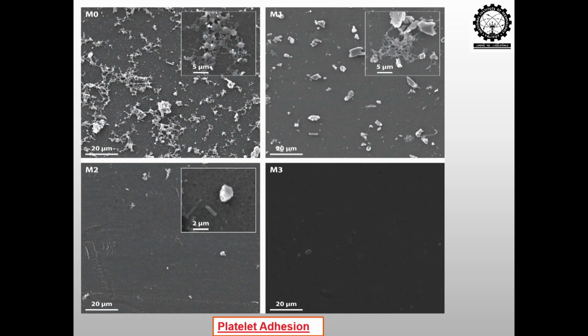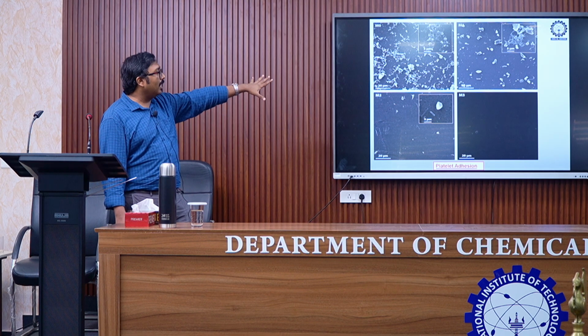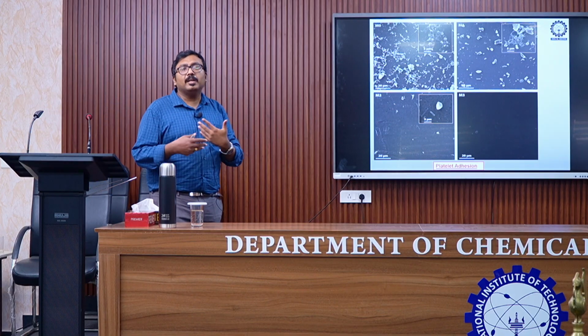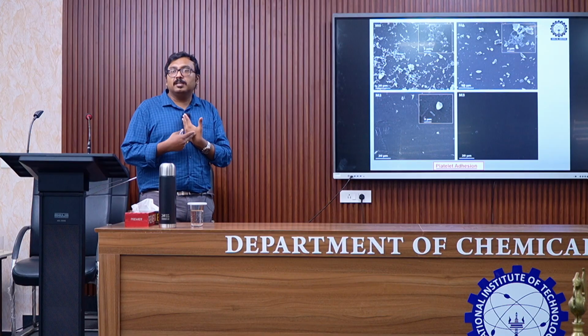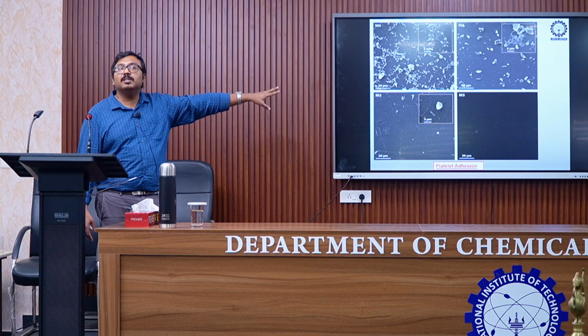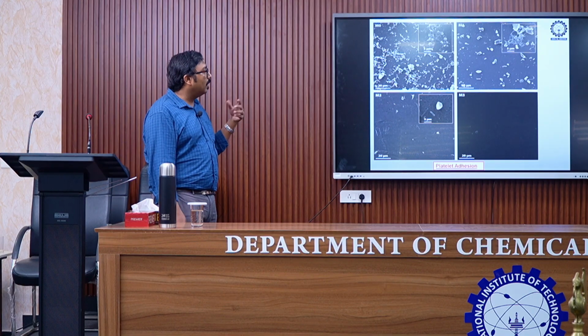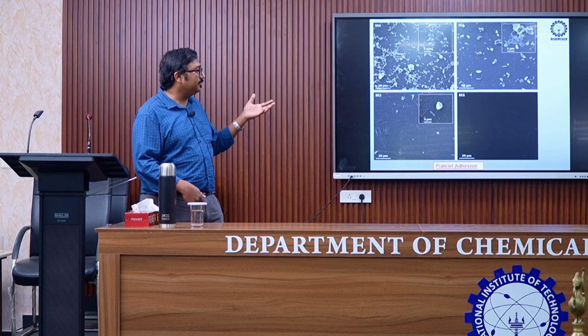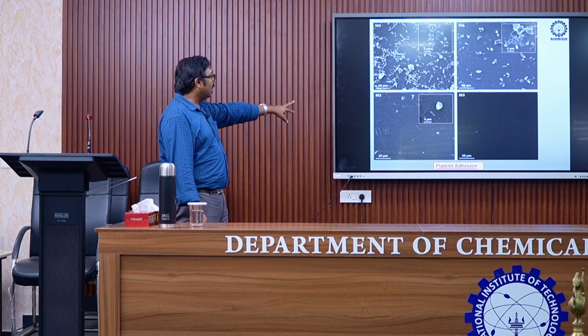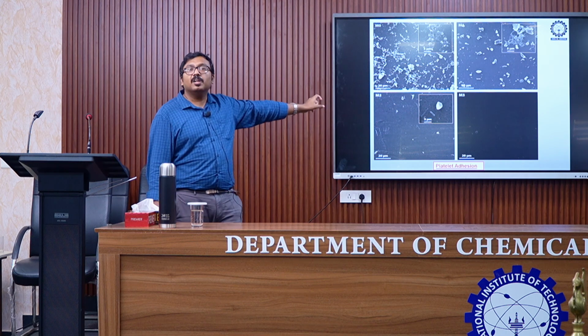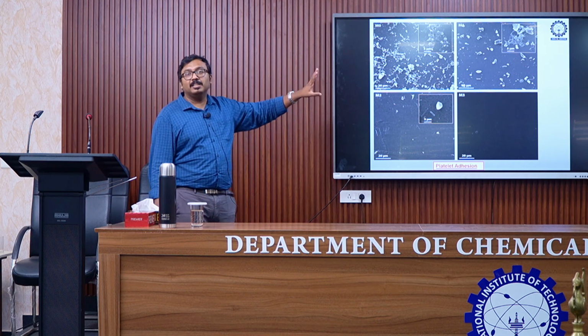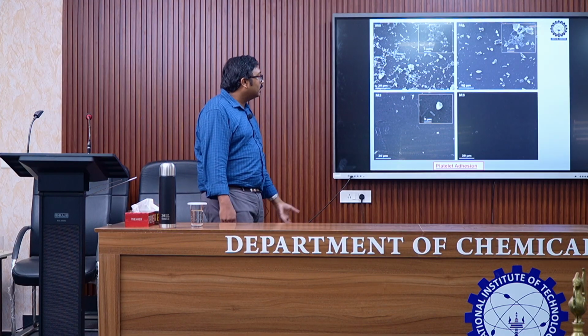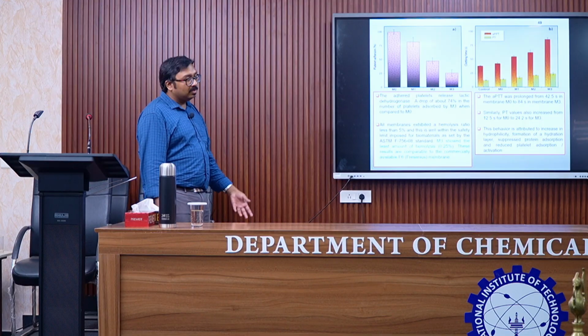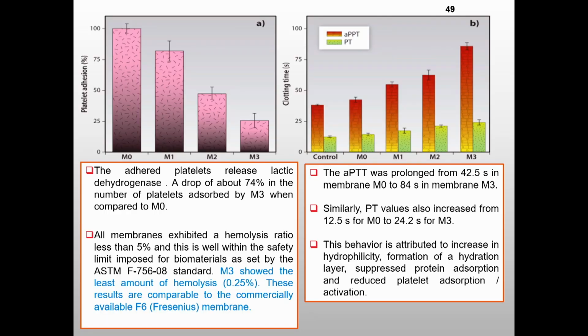Now platelets. On the first one, you can see that once the platelets adsorb on the surface, they start to form a network along with the fibrinogen. It creates a mesh. That is how actual clotting happens when we have a wound and the bleeding stops. That is a very positive thing, and that is what we require. But when we do hemodialysis, we do not want the blood to clot on the membrane surface. You can see that as the concentration increases, there are a few platelets adhered on the membrane, but they do not spread out, or they do not form the fibrin network. And at higher concentration, we are not able to see any platelets visually. So those are platelet adsorption as well as platelet activation.